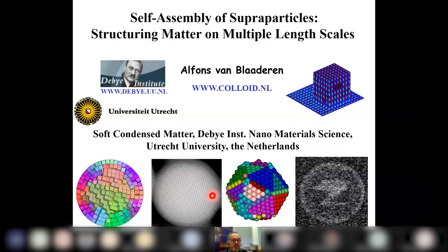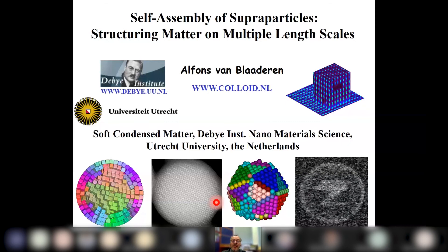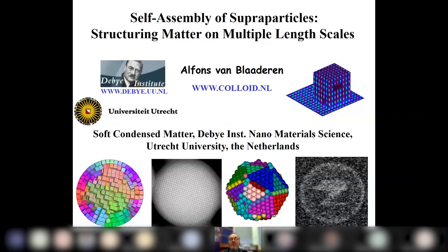This particle, where you see the laser pointer, has a diameter of about 300 nanometers, so in principle that supraparticle can itself be self-assembled again. A very important aspect of colloidal particles — tied to their definition — is that they can perform Brownian motion, meaning they have a well-defined thermodynamic temperature. Colloidal particles, if you know their interaction potentials, form the same equilibrium phases as atomic and molecular systems, making them very interesting both as materials and as model systems.